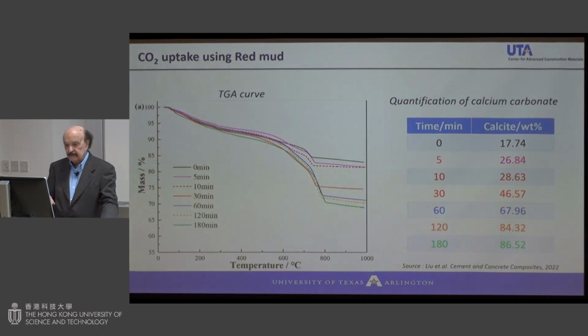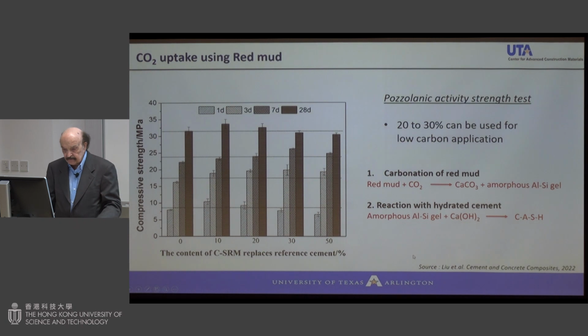So what happens here, for example, look at the right one, calcium carbonate, how long, CO2, I don't remember, I think it was 20%, but with more and more time, at about 3 hours, you have quite a bit of red mud converted into calcite. So then after 3 hours of curing of red mud, they add, I think, different amounts to replace cement. So here is the red mud, 0% to 50%, producing compressive strength from 1 day to 28 days. You can see with 10% red mud up to 20%, the 28-day compressive strength compared to control goes up. The reason is that after carbonation, red mud acts as a pozzolanic material, as shown here.